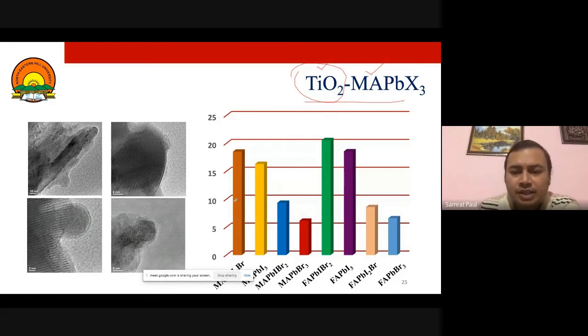So with these different materials, as you can see below, we have found their efficiency. So this is the efficiency versus different materials. So we can see the mixed phase, mixed halide perovskites. This is for methylammonium, this is for formamidinium lead iodide based perovskite. So they gave very good efficiencies for us. So we can see by just covering them with mixed phase TiO2, we are making two junctions here for the material. Here also in the TEM, you can see the different materials and different structures are there. So with this, we can really enhance, and these type of advanced materials can help gaining around 20% efficiency in